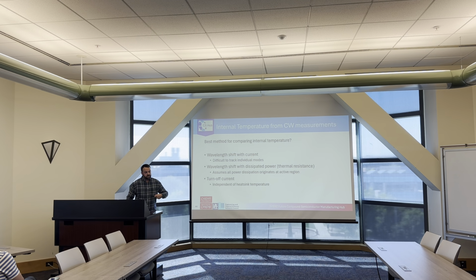So I wanted to verify as well that the internal mechanisms, or what's going on inside the device, is the same in the epi, so isolating the substrate effect. So I wanted to probe the internal temperature, compare that for GaAs and germanium devices, but there's a few methods you can use to gauge the internal temperature. You can look at the wavelength shift as a function of current, but over large current ranges it's quite hard to track individual modes. You get a scatter, you get potentially a sizable uncertainty, so you have a big uncertainty in your calculated temperatures then.